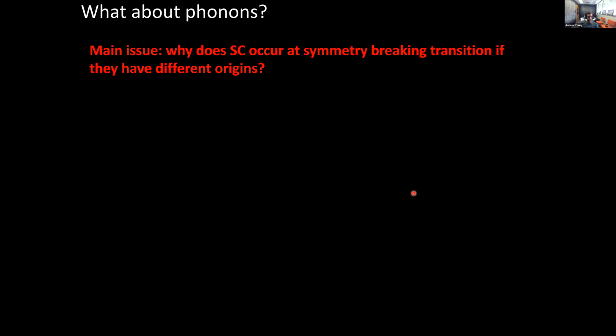what's the simplest thing that can happen, right? And the main issue with thinking, okay, can this just be a regular phonon-mediated superconductor? There are a couple of issues. Actually, one issue is that you're at extremely low electron density, right? So that's very different than typical superconductors, where your Fermi energy is very large compared to the Debye temperature. But in this superconductor, that certainly wouldn't be true.